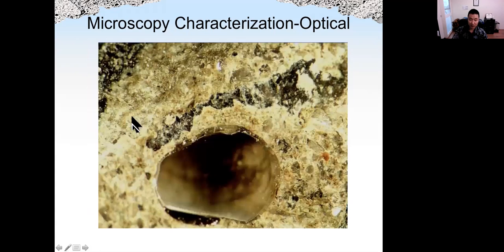Okay, so this is the gel in the voids. This is the empty air voids. You can see the gel generated inside empty voids. So if we put in air entraining agent, it will generate tiny empty air bubbles. So that may be beneficial to reduce the stress caused by this expansive gel. Okay, so air entraining agent may potentially reduce ASR.